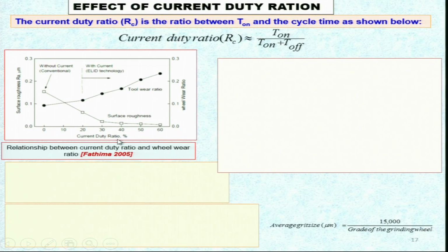This is the current duty ratio and this is the surface roughness Ra. You can see that the surface roughness continuously improves as the current duty ratio increases, and it stabilizes beyond a certain value, beyond 50 rather. On the other hand, wheel wear ratio continuously increases as the current duty ratio increases, because as the duty ratio increases, T on increases, and as a result the current pulse is acting for a longer time and the wheel wear is increasing continuously.